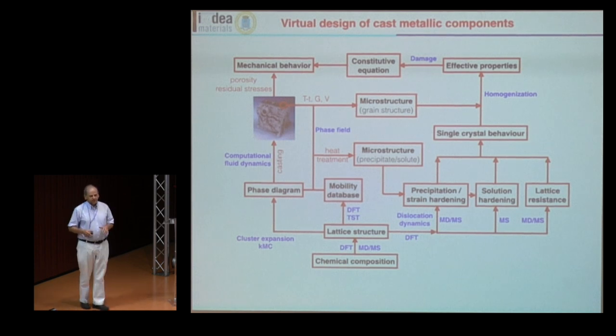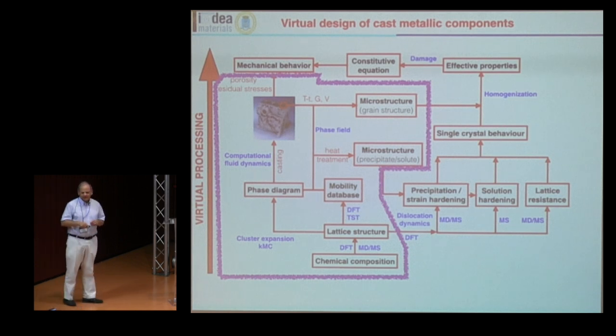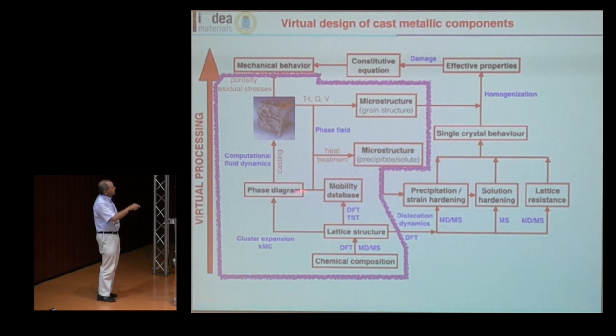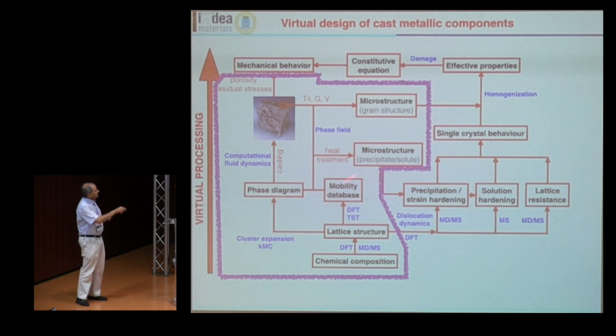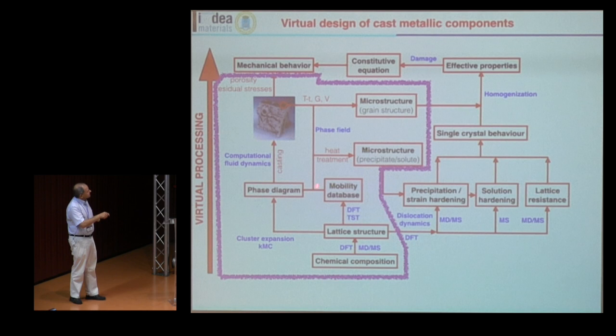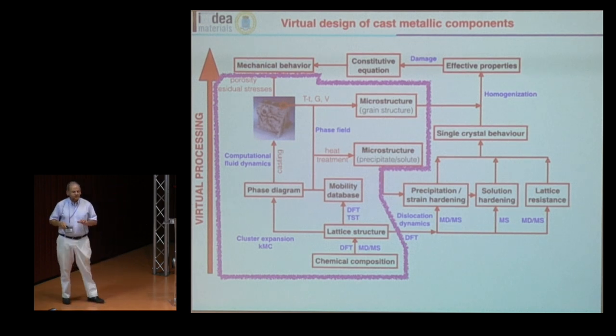This diagram has two parts. The first part on the left is what I call virtual processing. You begin with the chemical composition of the alloy, and using DFT and molecular dynamics you get the lattice structure; then using cluster expansion and kinetic Monte Carlo you get the phase diagram; and using DFT and transition state theory you get the mobility database. With this CALPHAD and DICTRA information, you go to your computational fluid dynamics code, fill the mold, and in each part of the mold you look at the temperature-time history, thermal gradient, and solidification velocity. With these parameters and phase-field modeling, you can predict the microstructure — including the amount, size, shape, and volume fraction of precipitates after heat treatment.